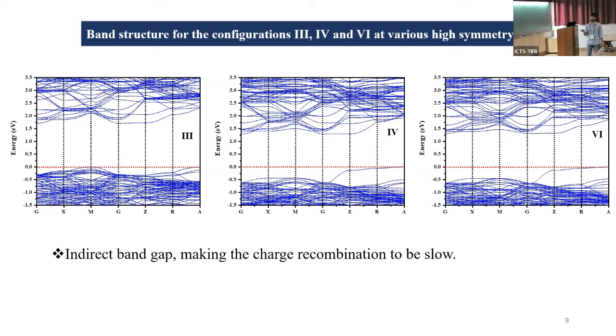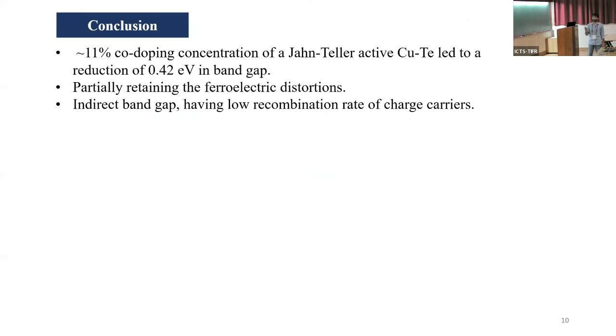And such indirectness also makes charge recombination slow, giving time for the generated charge carriers to be separated by the polarization in the system. With this, I would conclude that our co-doping strategy of 11% concentration of Jahn-Teller active copper and tellurium ion led to a significant reduction of 0.42 eV in the band gap, partially retaining the ferroelectric distortions, and the band gap studied was indeed found to be indirect, having low recombination rate of charge carriers, showing promise for future ferroelectric photovoltaic applications.